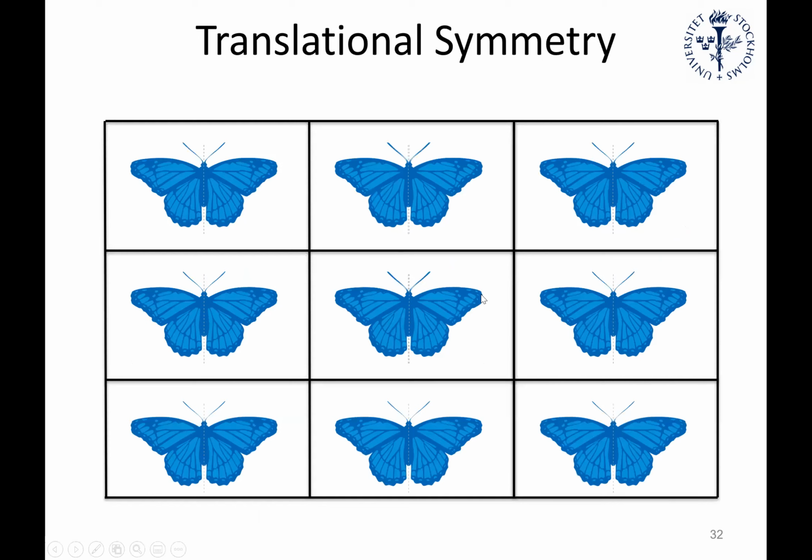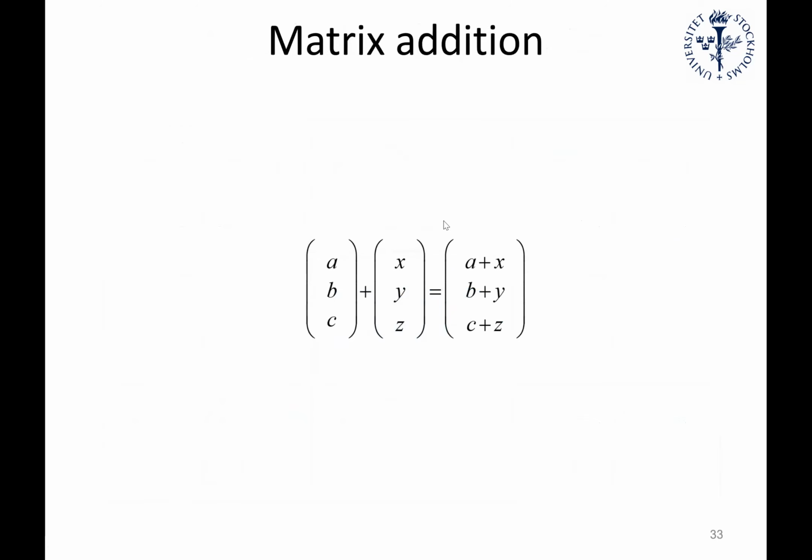Okay, so in 2-dimensional symmetry, we might have a 2-dimensional unit cell like this. We've already talked about 2- and 3-dimensional unit cells. But when we talk about translational symmetry, with the previous examples of symmetry like rotation and inversion, we did some matrix multiplication. Now what we're going to be doing is matrix addition to describe translational symmetry. So say you have, again, fractional coordinates x, y, z. If you want to translate it, then you can add a 3-by-1 matrix to it. So you can add your translational components A, B, and C.